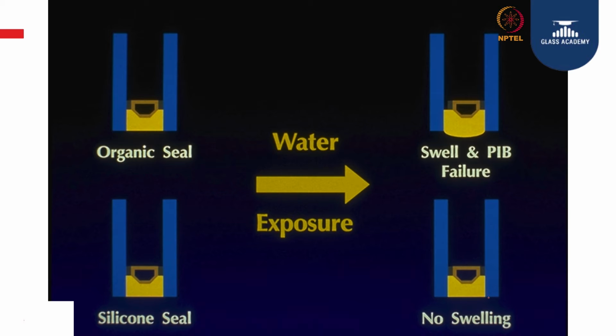The second thing is water exposure. When you have an organic seal and subject it to water, it tends to swell. Okay, they swell. When they swell and you try to move the units and push the two panes out, then the primary seal, which is not a load bearing member, will tend to fail. Once the PIB fails, you get a failure of the IG and then you get condensation. Whereas silicon seals remain exactly the same whether you expose them to water; nothing happens to the product.